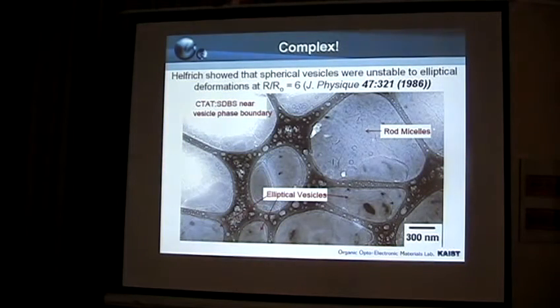But however, as I told you before, surfactant is really complicated. This is the cryo image I took when I was in Santa Barbara. But what I observed in the image is that actually the surfactant system is really complex. Even though I believe this is the micelle phase, this is the rod-like micelle phase, some systems cross over each other. And even though we think this is the micelle phase, some cylinders exist. This is from many experimental data. So I would say the surfactant system is a really complicated system.